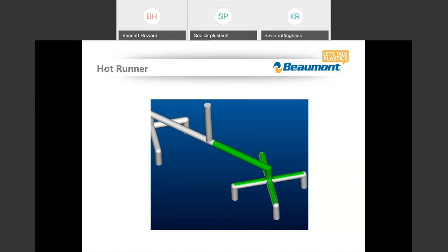So the larger your channel size, I don't know if that's necessarily the case all the time, but to say that your larger diameters are less affected by shear, the answer to that is yes. But understand that that's just one part of the equation. We have to understand what the specific viscosity variations are for that type of polymer. Someone mentioned earlier LCPs are much more affected by shear rates versus maybe an olefin. Also, how long that runner is. You might have a very short, chubby runner versus a very long, skinny runner that's going to be affected differently. But if you have a chubby runner over a very long flow length or a long, large sprue over a long flow length, you can still end up with a severe shear profile. Shear, when we talk about shear and how we calculate shear, isn't just temperature, it's also time.